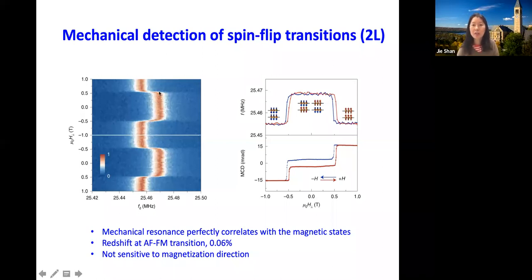And as you can see here, the resonance frequency has a jump around the half Tesla. And this figure captures the resonance frequency. And the width actually doesn't change too much. Also, within this range between 0.5 Tesla and negative 0.5 Tesla, amplitude or width basically don't change. The only change is this sudden redshift in the resonance frequency around 0.5 Tesla.